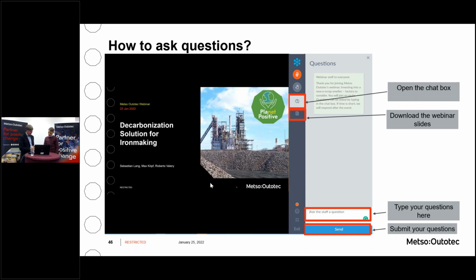Yeah, so the key message is it's not only what we had in Trinidad, with what was more or less a sinter feed. It is really also finer concentrates, finer material, which can then be treated by microgranulation to get the size distribution what we need. Correct. And that we have tested intensively in the lab in the past.